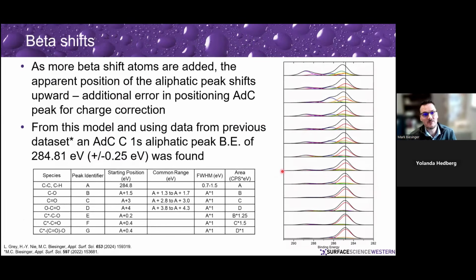If I go back to that beta shift problem, as you add more oxygen in your adventitious carbon, so up here we have a lot of oxygen species, the positioning of that main peak shifts. If we have very little oxygen in that, the alkane peak and the peak maximum of that main peak are very close together. They're going to be about 284.8 bang on. As you add oxygen, these beta shifts move the apparent position of that peak maximum over quite a bit, as much as 0.3, 0.4 eV.